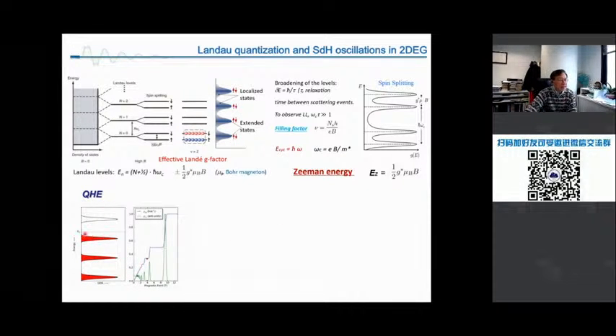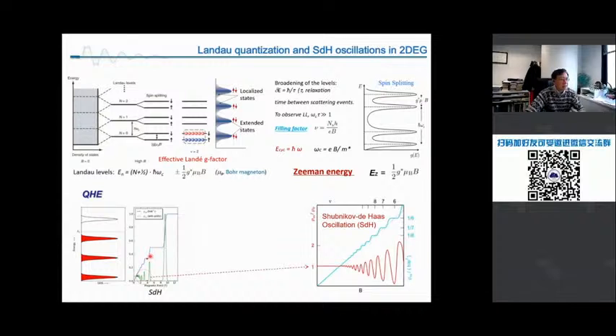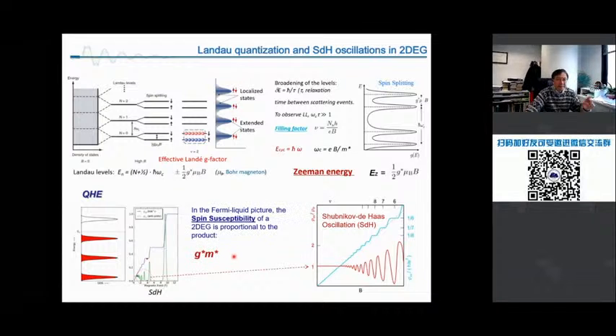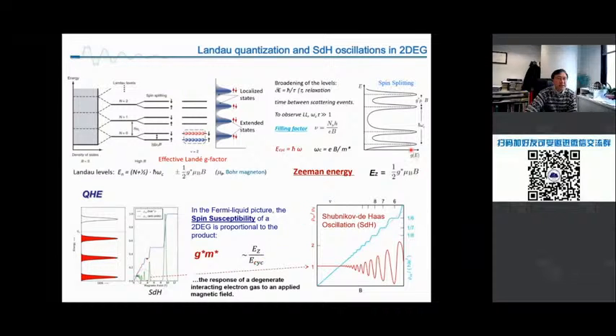So the quantum states that you measure is basically you set the Fermi energy level in the gap, that is plateaus, but in the Landau levels, you see a peak and so on. If the quality of the material is not good enough, you see first the Shubnikov oscillation that represents the same things. So I'm going to introduce one thing. It's about the spin susceptibility, basically the G factor. How to measure this? This G factor is represented by the ratio of Zeeman energy and the cyclotron energy at the level. That represents the response of the degenerate interacting electrons once you apply the magnetic field. All right, so this is the principle.